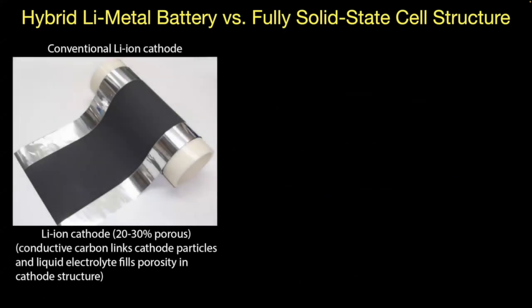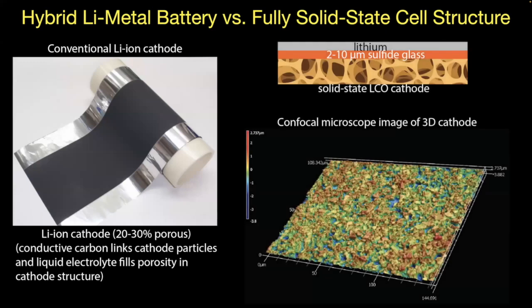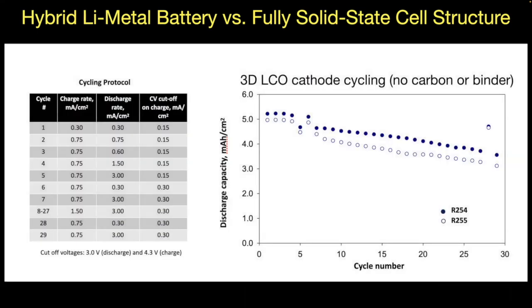And that approach looks something like this. Here on the left, that's a conventional lithium-ion cathode. And on the right, this is what we're doing. That confocal microscope image is actually LCO, so there's no carbon, no binder. There's a three-dimensional structure with porosity. And the first tests we do on the cathodes are actually with liquid. And you can see that we get very good cycling. So we're moving about 5 milliamp hours per square centimeter, again, at reasonable rates.